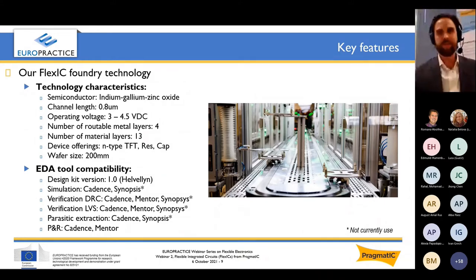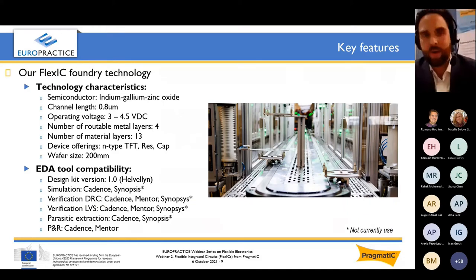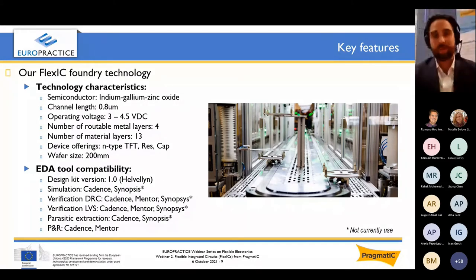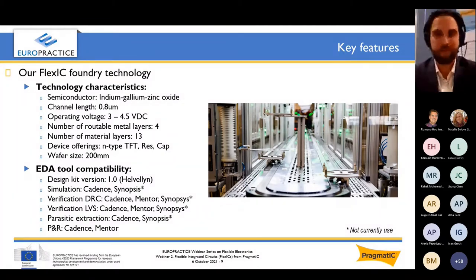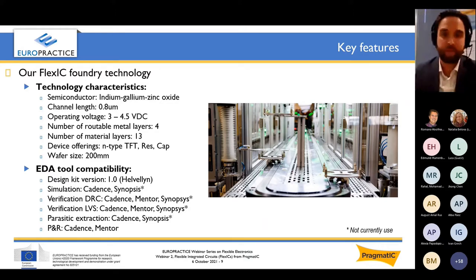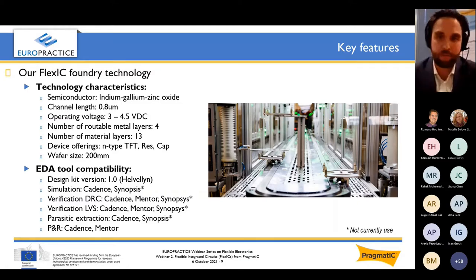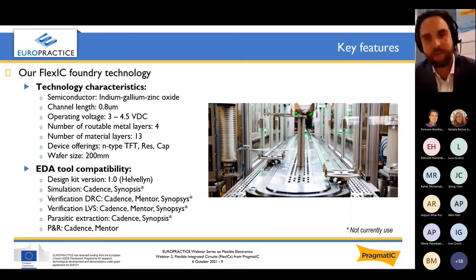Talking about the manufacturing process: we have an N-type metal oxide TFT technology based on IGZO. We have also demonstrated CMOS at the R&D level, though it's not yet available on our production line. Our manufacturing process remains NMOS, but that still opens a lot of opportunities. We use 200-millimeter wafers, running several sequences of material deposition, patterning, and etching. We are not a printing technology — we are very close to conventional semiconductor manufacturing and use industry-standard tools. Today we can achieve 800-nanometer channel length, with scope to lower that to a few hundred nanometers in the next few years.